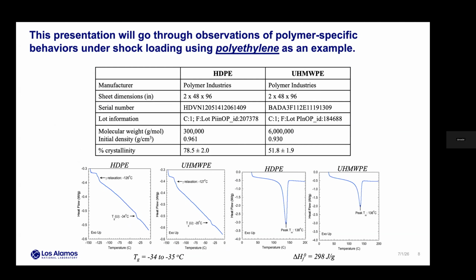So the two types of polyethylene that I'm going to focus on today are high density polyethylene, which is like a typical milk bottle. The thing I want you to remember about high density polyethylene is that the reason it's high density is because it's highly crystalline. So the material that we studied was nearly 80% crystalline. So if you think about the spaghetti structure, almost 80% of the material is organized into these crystalline domains that have order associated with them. And the reason that they can do that ordering is that the molecular weight is not very high. It's about 300,000 in this case, for the material we studied.